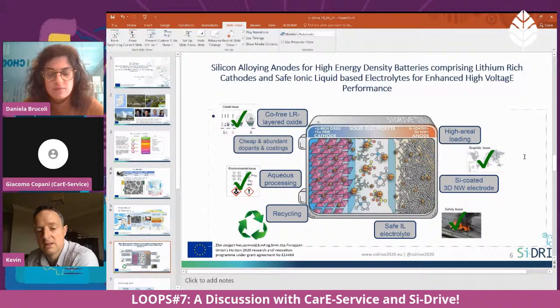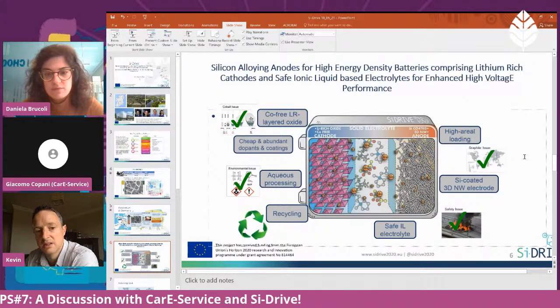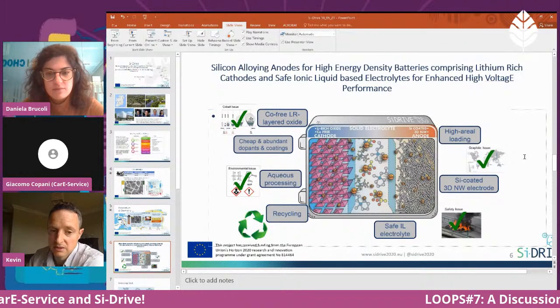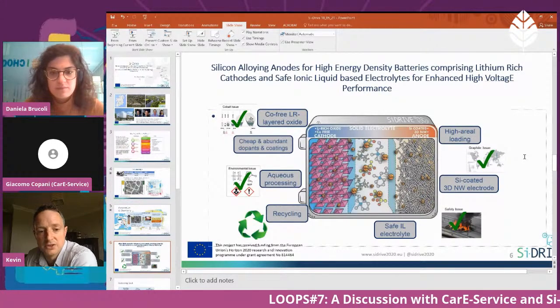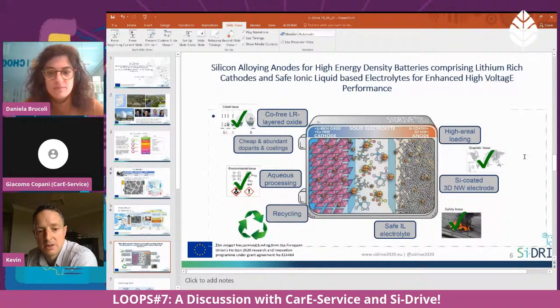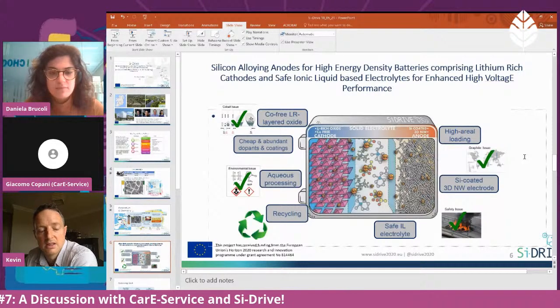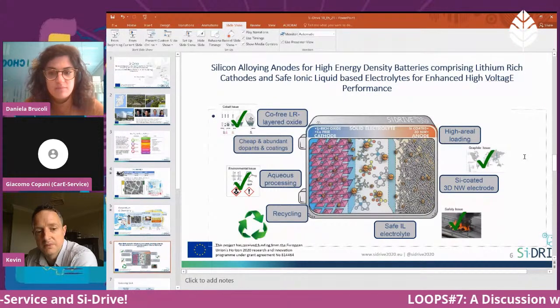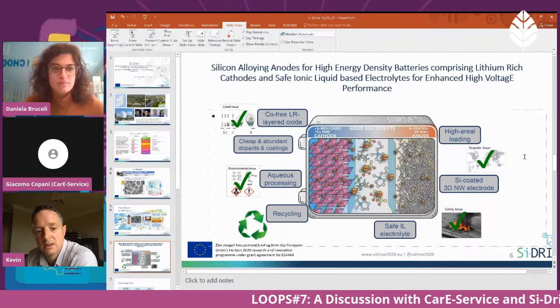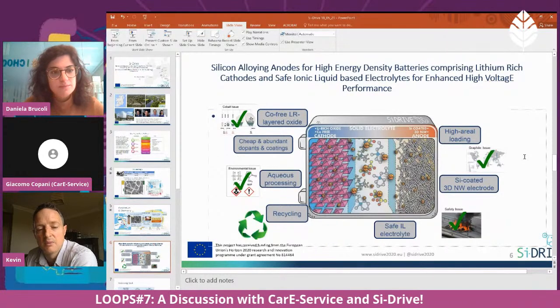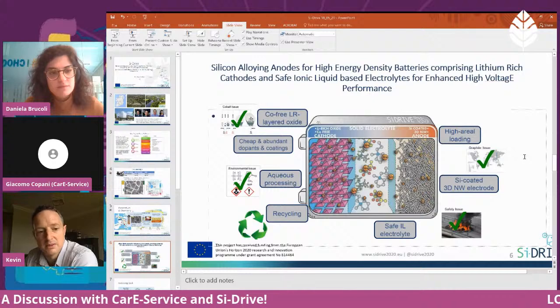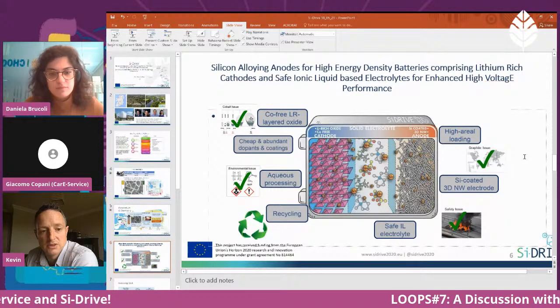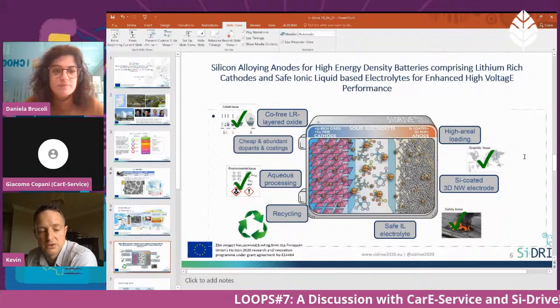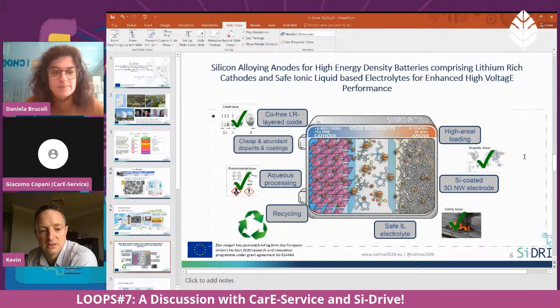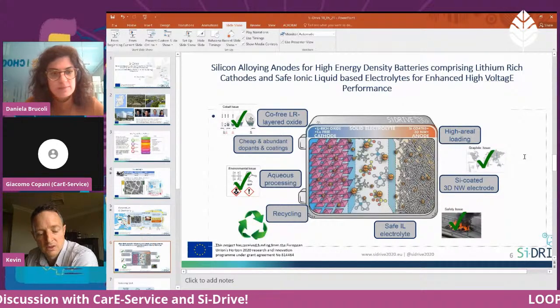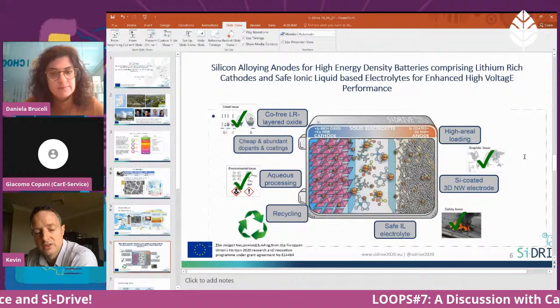So by doing 100% silicon, directly grown from the electrodes, we're eliminating a lot of the binders and the conductive additives. And then on the cathode side, because it's cobalt-free, there are a lot of ethical issues in terms of the use of cobalt, because there's child labor used in the mining practices in the Congo. So being able to achieve a high performance battery that's cobalt free is hugely important. And part of the modeling and the experimental aspects is to optimize these electrodes with dopants and coatings to improve performance, such as the SEI issues, and I'll speak a little about the results on that. We also have aqueous processing, so that addresses the environmental issue.